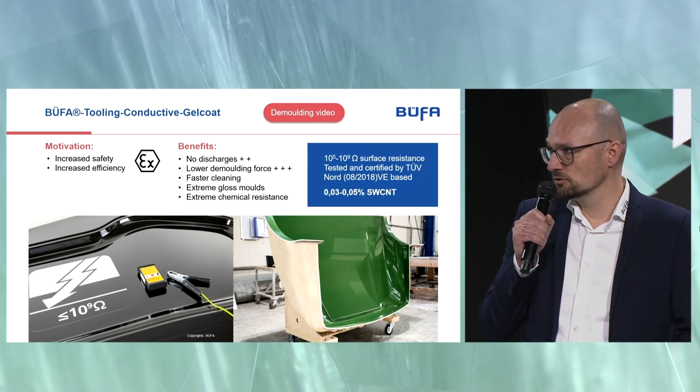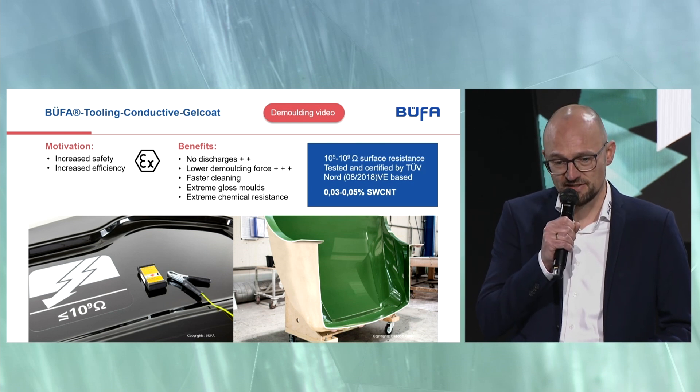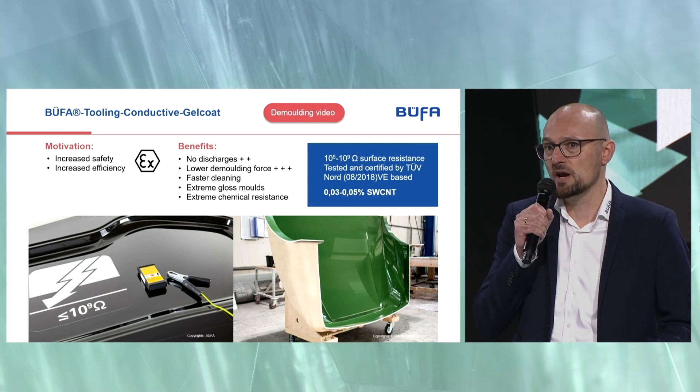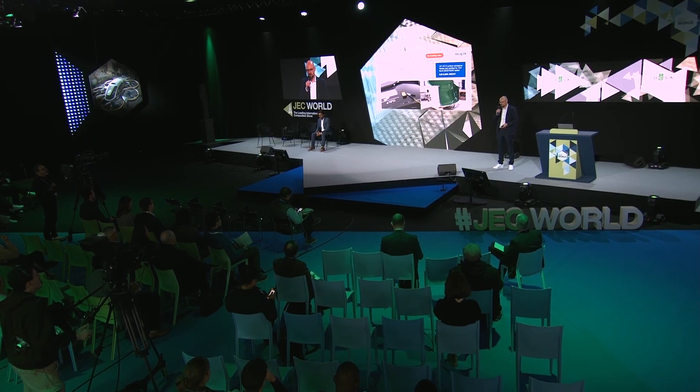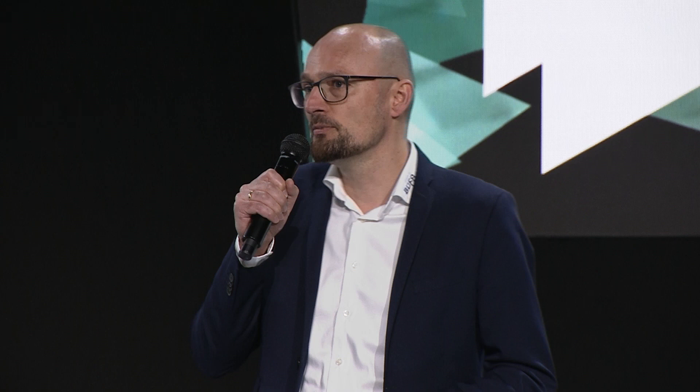We also use this technology to create conductive tooling gelcoats. The motivation is to increase both safety and time efficiency. With a conductive mold, there are no discharges during demolding, which increases safety and eliminates flashes. We also notice a much lower demolding force required. The risk of any damages is greatly reduced if the mold surface is correctly grounded. Dust adhesion is significantly reduced and the cleaning step goes much quicker. These molds also achieve a higher gloss level than all other molds we tested, and they have extreme chemical resistance as they are based on vinyl ester resins.